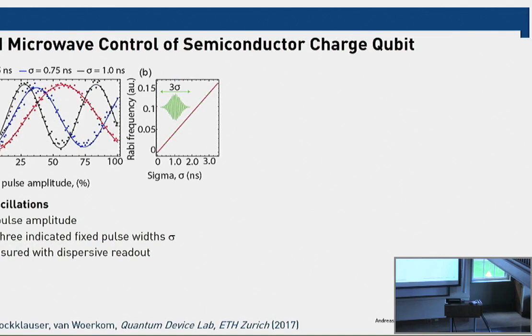So here's a set of Rabi oscillation measurements that were performed this way. So you pulse a microwave source that is resonant with the charge transition in the double quantum dot, and then you send a second pulse applied to the resonator, and based on the phase and amplitude of that pulse, you extract the qubit occupation, which is on this axis here. And we decided to do Gaussian pulses here and choose a sigma of the Gaussian pulse, which is shown here, and change the amplitude of that Gaussian pulse. So we do Rabi oscillations not by changing the length of the pulse, but by changing the amplitude of the Gaussian pulse. And then you can check how the Rabi angle depends on the width of that Gaussian pulse, and verify that it's linear as it should be.